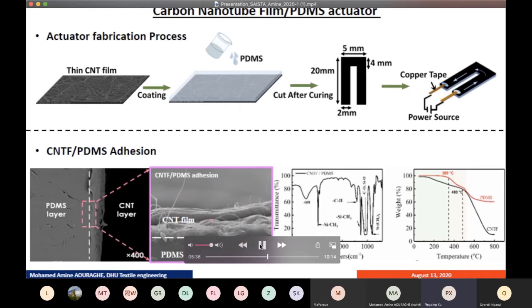From the FTIR test, new silicon groups appear on the composite, which were formed mainly from the PDMS polymer. In addition, the TGA test demonstrated that PDMS starts degradation after 300 degrees before totally degrading after 500 degrees, which demonstrates the limits of the fabricated composite.